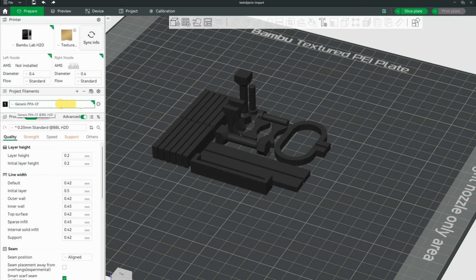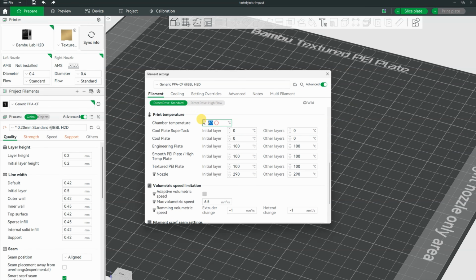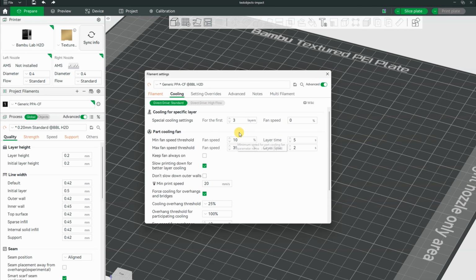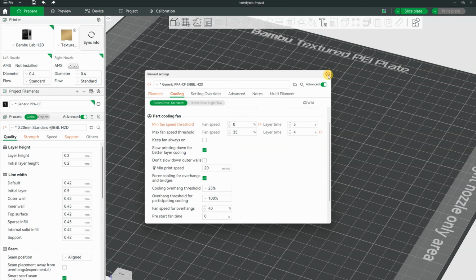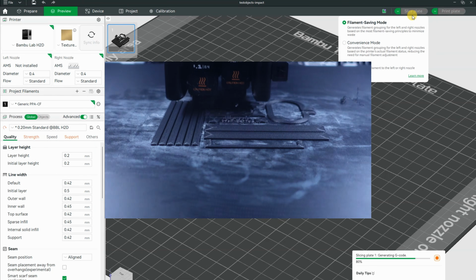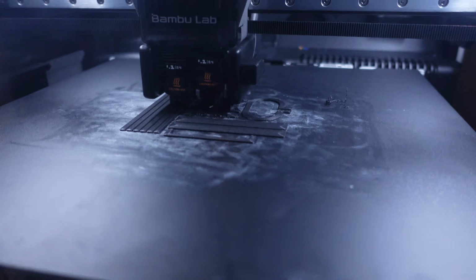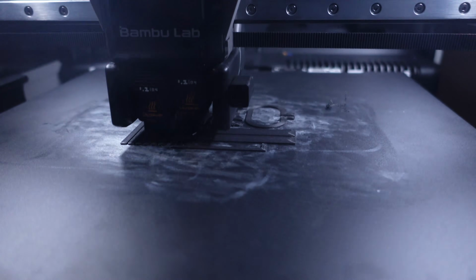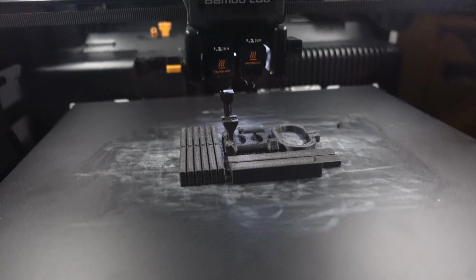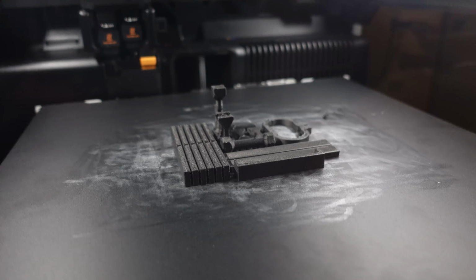Slicer settings. I started from the generic PPA CF profile, chamber 60 degrees Celsius, on the bed 120, nozzle 320 as maximal recommended, maximal flow 10 cubic millimeters per second, cooling between 0 and 35%, and I increased the minimal layer printing time to 4 seconds. My regular test objects. The start is good, but I maximize here several temperatures, bed and the chamber. Not the cleanest printing. Maybe I could dry the filament, but it's too late now.